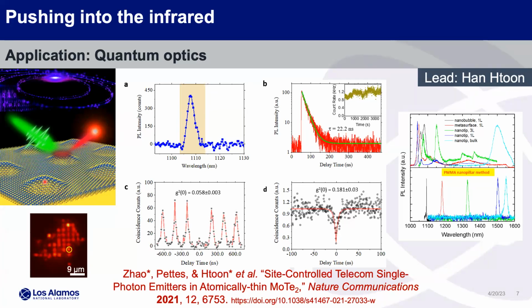He did dry transfer. He did not do this inside of a glove box. We do have a glove box with a robot that you can transfer 2D materials, but he just did it by hand in air and went straight to the measurement chamber. And we found that you could actually change the emission lines from their normal exciton and trion states here, all the way out. The sharp lines are always closer to the band edge here, but you could also get broad lines out to like 1550 or so. So what we found is with my technique that's super sharp, everything's kind of broad, but with these nanopillar techniques, you have things that are sharper. The only problem is because you can't make an exact circle. You can if it's bigger, but these are like 200 nanometers, so you're not going to have it perfect.